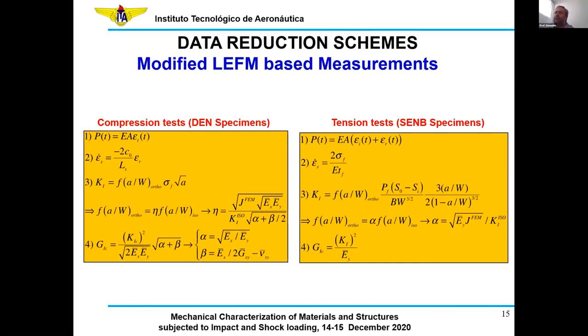It is worth mentioning here that when we compute the stress intensity factor by using the standardized expressions for metallics, these commonly used expressions do not account for orthotropic effects. Therefore, from the direct measurements of the KI using DIC, we proposed a new correction function which accounts for orthotropy. We can correct the effects of orthotropy in trying to get our stress intensity factor. This correction factor is obtained from FE simulations.